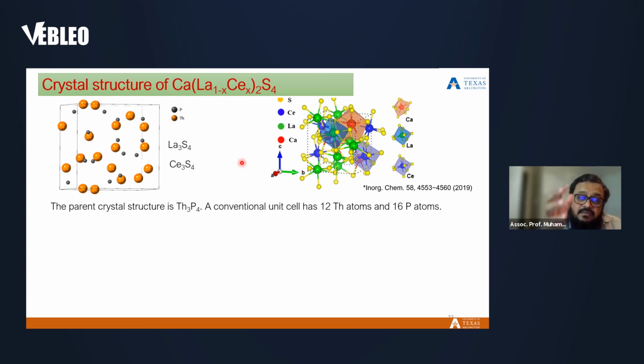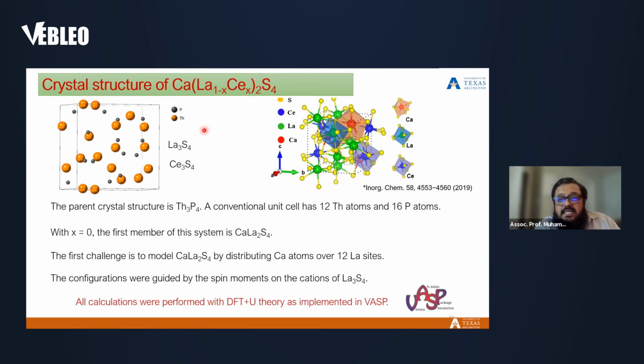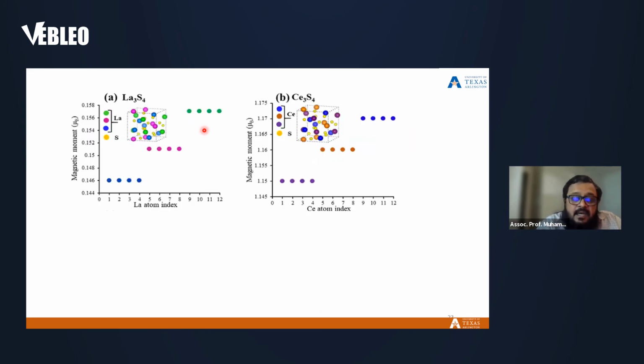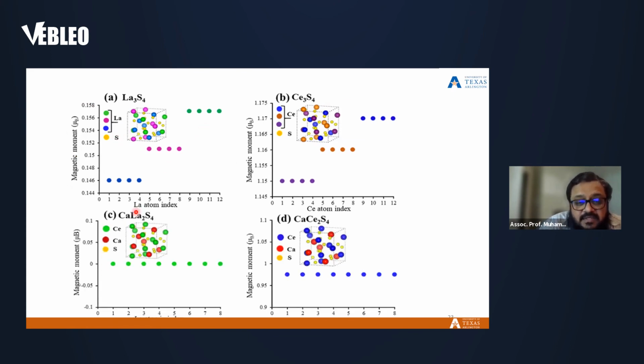So when we calculate it, we take the same structure, like lanthanum cerium sulfide. The question is why calcium is in there. One of the reasons why calcium is in there, and it's an experimental result, is that if we have calcium, then the synthesis temperature for the lanthanum sulfide or cerium sulfide becomes lower. That makes them easy to synthesize. Now that's an experimental result, and our recent publication also shows why calcium does it.